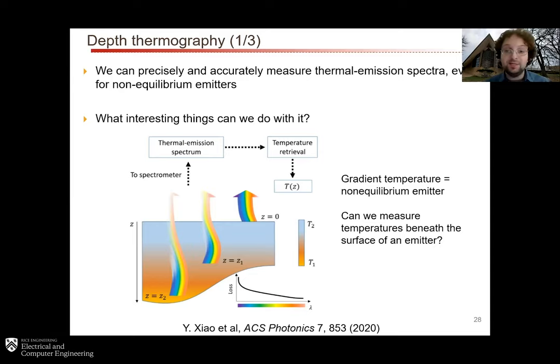So in addition to these black body type references, we also have a couple of standards that we're very used to in the lab, just because we've measured them over and over and over again, and you probably will see them pop up throughout my talk, which is we use sapphire and we use fused silica wafers. Those can be polished so then you don't have any sort of scattering or roughness uncertainty. And as long as you know very, very well what the emissivity is, you can use them as references. There are a few issues with those.